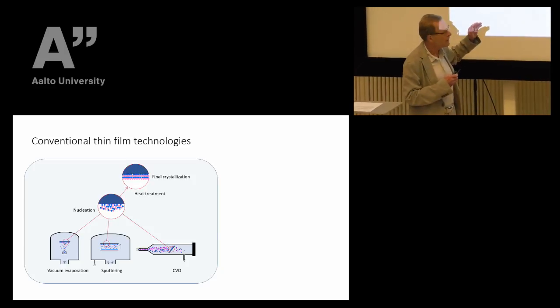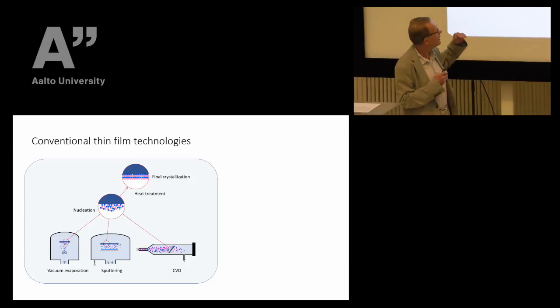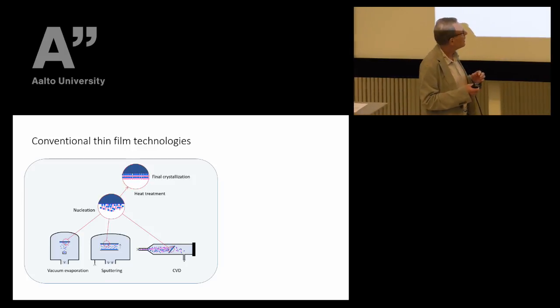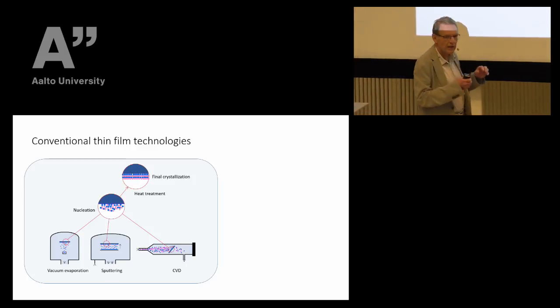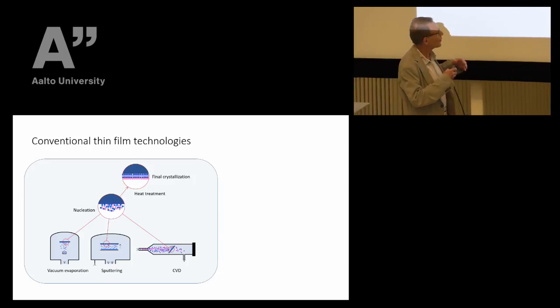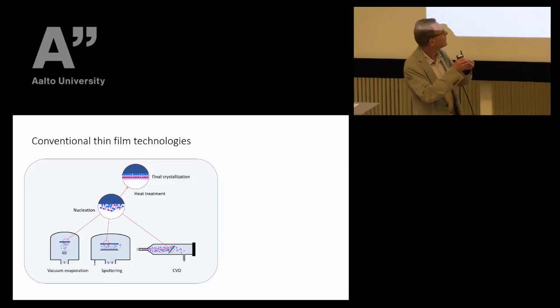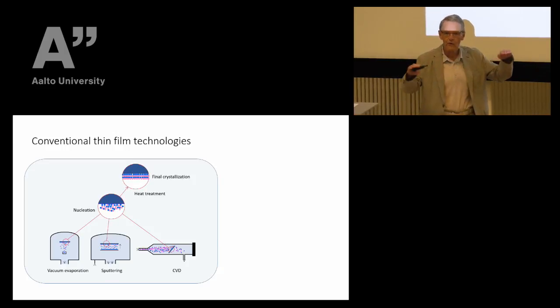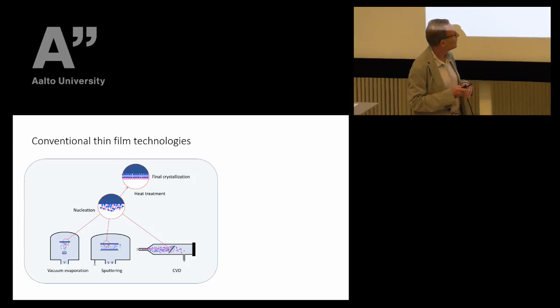So it means that we don't have any major ways of controlling the build-up of the material on the substrate. So there's some kind of three-dimensional nucleation where molecules are looking for energetically optimal sites with their neighbors, and then we might need some kind of heat treatment in order to improve the crystallinity and get the film as uniform as possible.